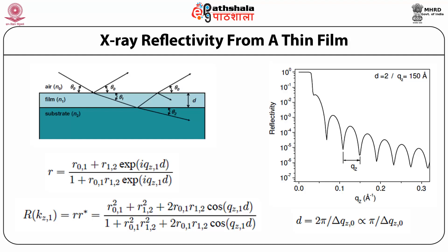These oscillations are a signature that we definitely have a film over a substrate — usually the film is so thin it cannot be seen by eye or even by microscope. When you do the scan and observe oscillations, you can be sure the film is there. We can estimate the thickness of the film from the fringe spacing using the formula d = 2*pi / delta_Q.